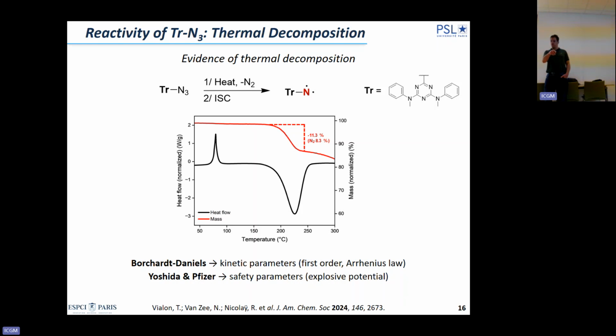Here you have the temperature, and you can see that the molecule around 200 degrees Celsius loses approximately 10 weight percent, which corresponds approximately to the weight percentage that you would expect if you lose N2. Of course, under these conditions, the nitrene we make may be a bit volatile, so we expect to have a small loss. So this is compatible with the loss of N2, which was expected.